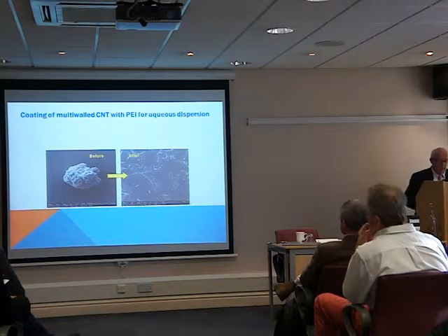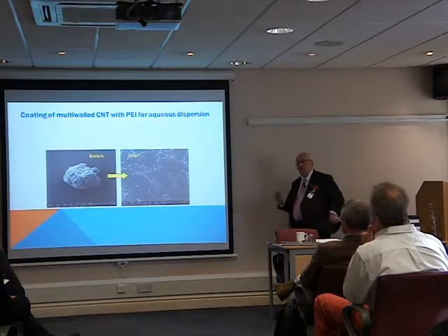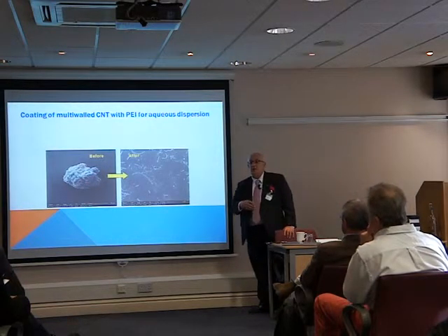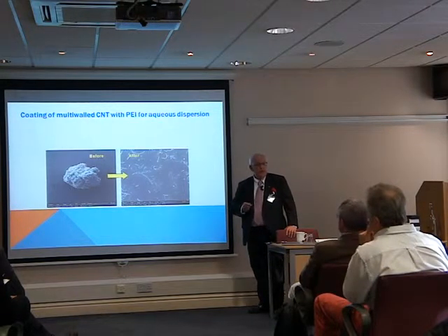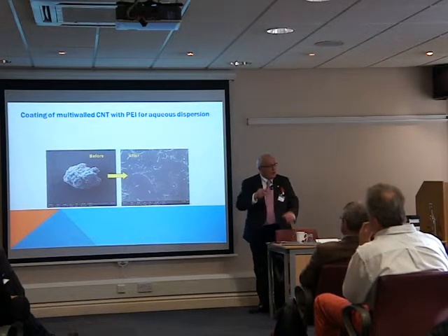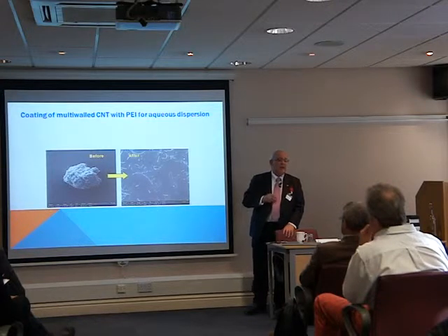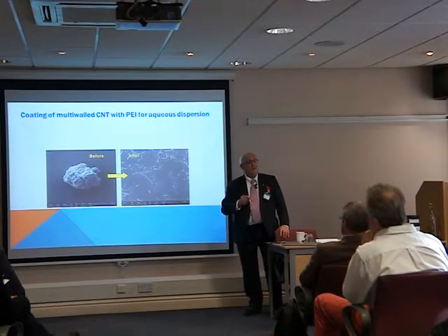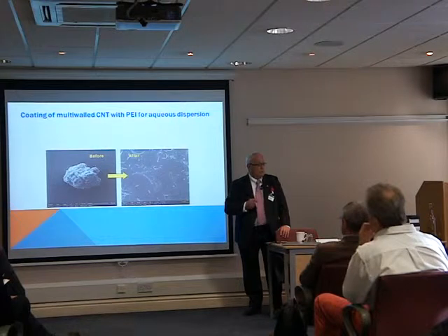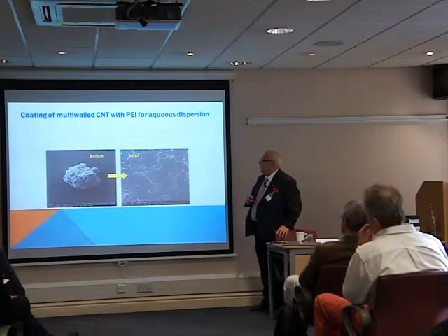Problem with carbon nanotubes in particular, and these are essentially graphene sheets which are rolled as tubes, either as a single tube, single wall carbon nanotubes, or as multiple concentric tubes. In point of fact, for medical applications, the single tubes are useless because they break so easily and they are imperfect. So in essence, we use, for biomedical application, multi-wall carbon nanotubes.